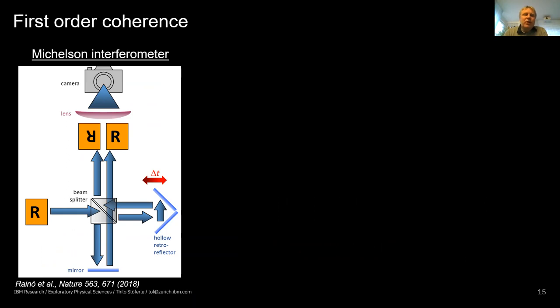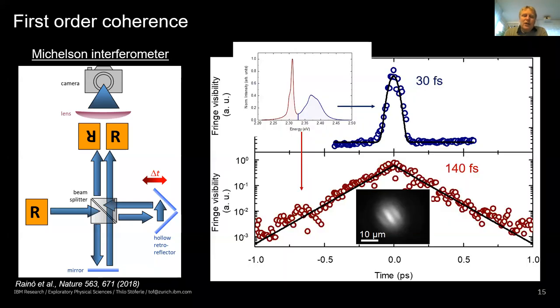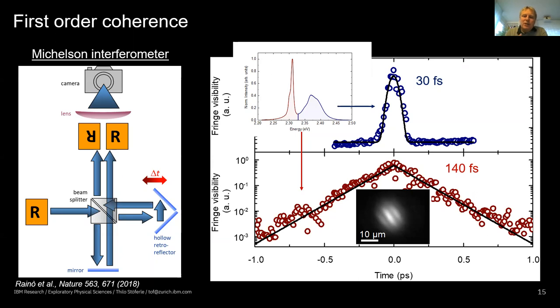The superfluorescent state has enhanced coherence properties, measured using a Michelson interferometer from our polariton experiments. Comparing coherence times from the blue uncoupled peak and the red coupled peak shows a significant difference. However, the coherence from the red peak is not as long as expected, which we attribute to having several superfluorescent domains that emit independently from each other, destroying the coherence. With just one superfluorescent domain, you would expect coherence time on the order of the decay time, but multiple domains shorten this.